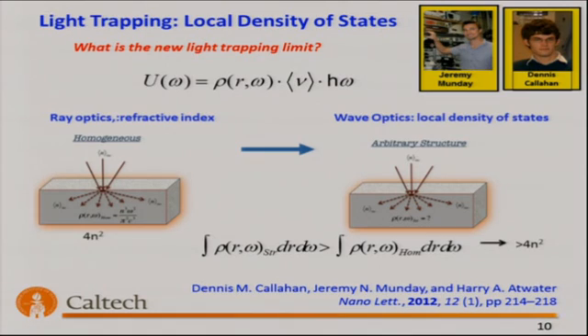So recently, our group took a slightly different picture. It's all related in the end, but it's also useful to think in terms of the electromagnetic energy density, in terms of what we call the local density of states, the density of modes that are present at any given particular point within the medium, times the mode occupation times the energy per photon. And when we think about the local density of states for a homogeneous material, you have this Rayleigh-Jeans type expression for the local density of states, and it's the same as the density of modes uniformly throughout the material.